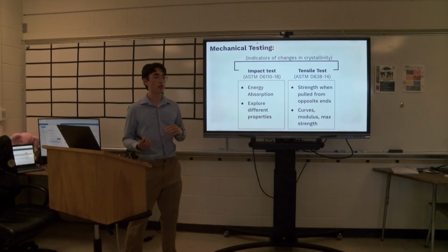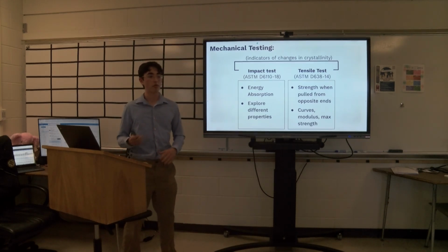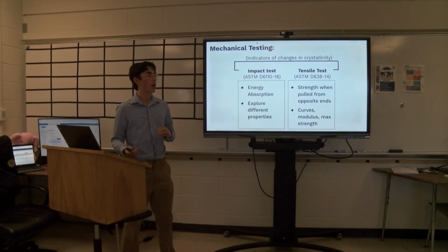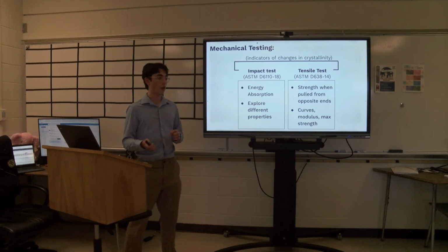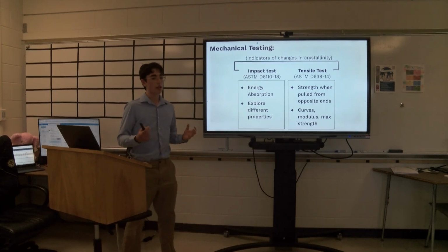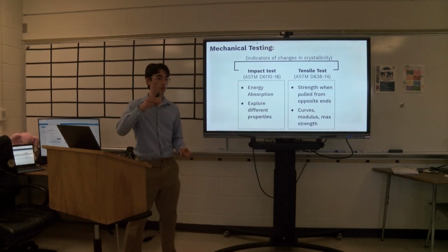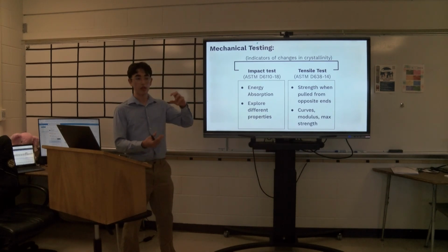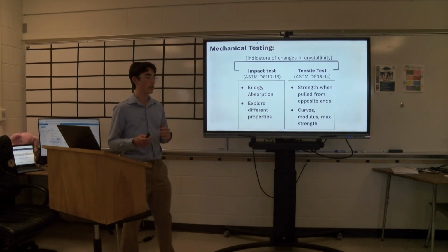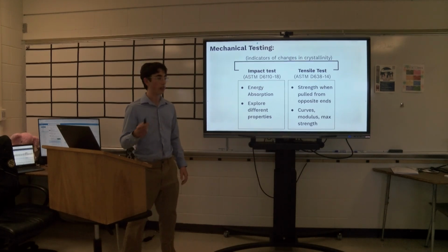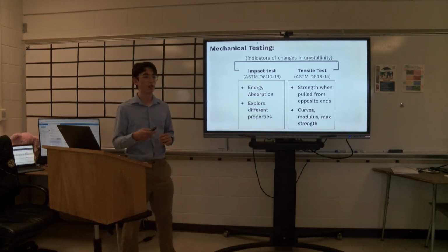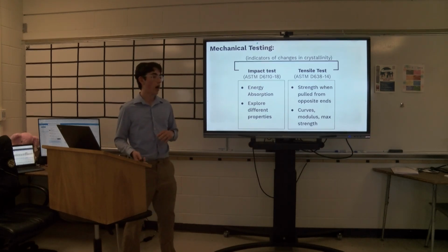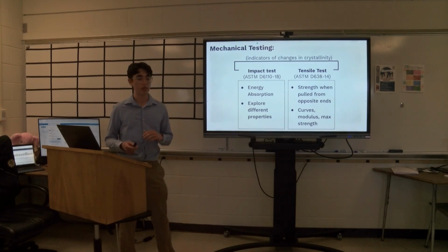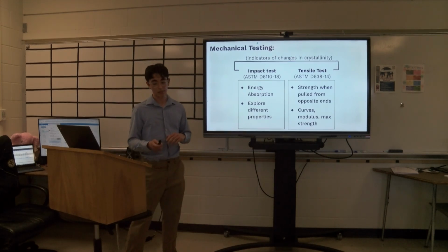I chose the tensile test mainly for its prevalence in the literature and for the number of data points I could get from it that could be used to compare and gather data on how they could perform in the real world. In this test, it's essentially the strength of a dogbone specimen while it's pulled from two opposite ends, and you measure its strain, which is how far it's stretched, and how much force it's taken to do that. As for the impact test, this test measures the energy absorption as a pendulum is swung at an object, and I chose this test to explore a different set of mechanical properties in comparison to the tensile test, and also explore the cases where sometimes the recycled material would have a higher impact strength.